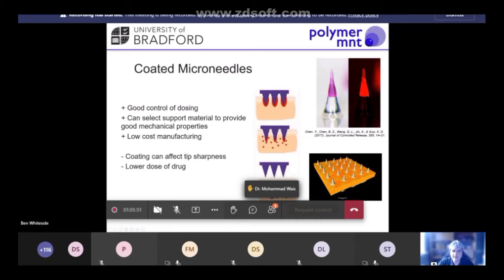And also, it's pretty low cost manufacturing. We can mass produce the microneedle array. Dip coating systems are fairly straightforward to actually coat these needles. And that gives us a fairly low cost manufacturing chain to make the devices in the first place. The slight downsides are, as you can see, if you've got a sharp tip and then you place it into a coating, that's going to slightly reduce the tip sharpness, which is going to impact your penetration behavior slightly.